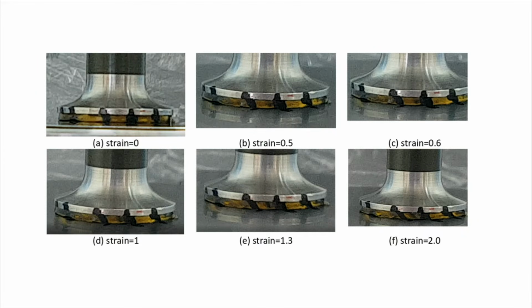And this is slightly different. We want to characterize this yellow piece of polymeric material here. How we're doing this, we're putting it on a stationary surface, and then we have this spindle on the top, which will rotate. So you're basically twisting your material, so you're shearing the material. And these are called rheometric tests, as opposed to mechanical tests, the ones I showed you earlier. If your material is very soft, so we said a lot of these materials are on the boundaries of solids and fluid, this could be your only option of probing the mechanical response of the material.